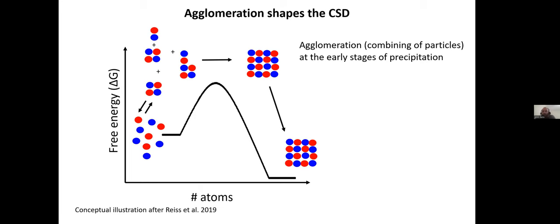So what we suggested during my first paper I wrote in the PhD was that the unstable nuclei that form go through agglomeration, which is combining of particles, and they could create crystals by agglomeration that do not go through the critical size. By agglomeration, they could create crystals that are much larger than the critical size, and when they start crystal growth, they're already larger, which would also explain why there are fewer of the large crystals. Now, this has to happen at the early stages of precipitation, because I showed you that the aspect ratio during growth of a crystal is constant, and agglomeration would change that ratio. So this has to happen at this stage.